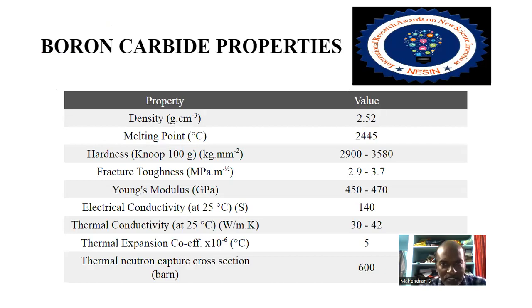The properties: density 2.52 gram per centimeter cubed, and melting point 2445 degrees Celsius. Hardness 2900 to 3580. Fracture toughness 2.9 to 3.7. Young's modulus 450 to 470 gigapascal. Electrical conductivity 140 siemens. Thermal conductivity 30 to 42 watts per meter Kelvin. Thermal expansion coefficient 5 degrees Celsius. And thermal neutron capture cross section 600 barn. These are the boron carbide properties.